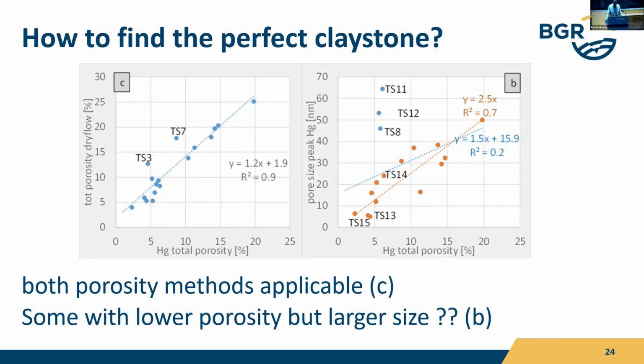And you can see here that there are some samples which do not follow the main trend. Normally, you would say that as the porosity goes down with increasing burial depth, as we've seen before, the pore size should do as well. But the sample TS11, for example, or 12, right? They have a quite low porosity, but a relatively high pore size. So why is that? The idea was then that it could result from cementation.